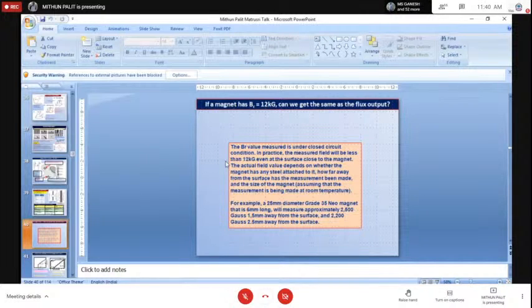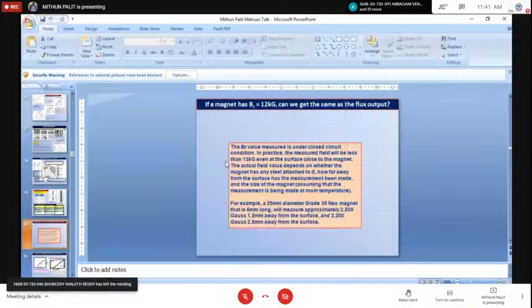Well, if I have been given a magnet with 12 kilogauss field, I just want to ask you, whether we get 12 kilogauss at all in the application. Because if you keep that magnet in the air and measure the magnetic field starting from the surface of the magnet, we can see that the magnetic field decreases drastically. So you can see here that a 12 kilogauss NdFeB magnet with a 35 energy product grade can give approximately 2500 Gauss field 1.5 millimeter away, and 2200 Gauss field 2.5 millimeter away.